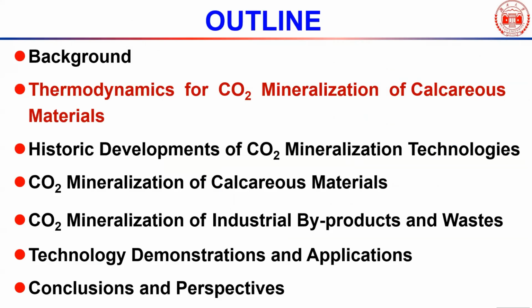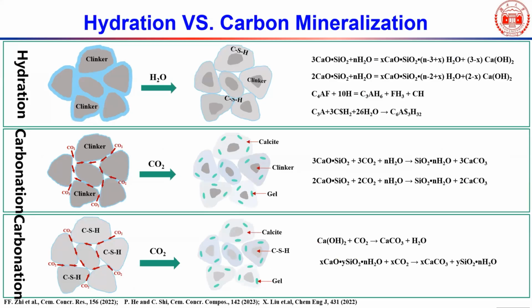Now let's have a look at the scientific basis, basically the thermodynamics of carbon mineralization of some materials. Here you can see some charts. The first one is the conventional hydration or hardening of concrete, where cement clinker reacts with water to form calcium silicate hydrate and some other hydration products. The second one is the clinker carbonated directly, but in the presence of moisture. Then we mainly get calcite and also some silica gel. The third one is hardened concrete, mainly calcium silicate hydrate, reacting with carbon dioxide, which then also forms calcite and C-S-H, some leftover, and also silica gel.